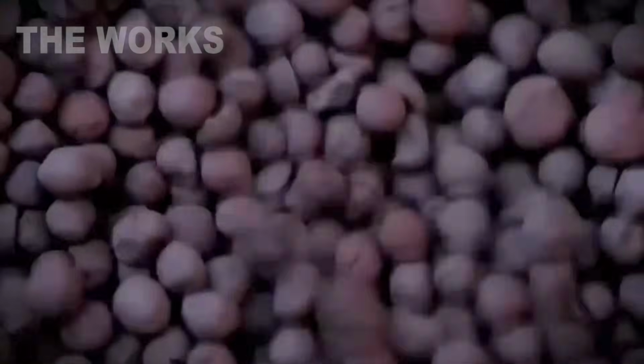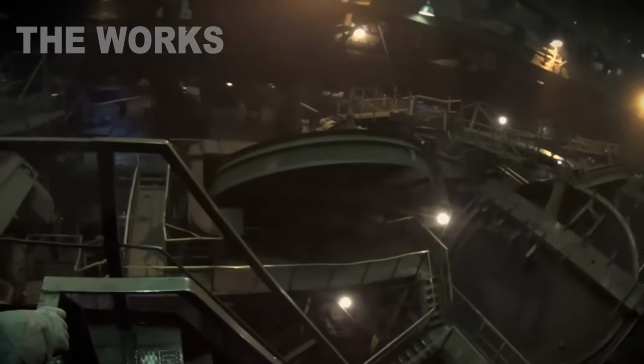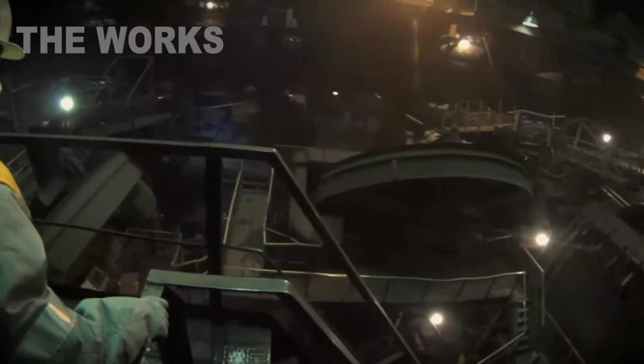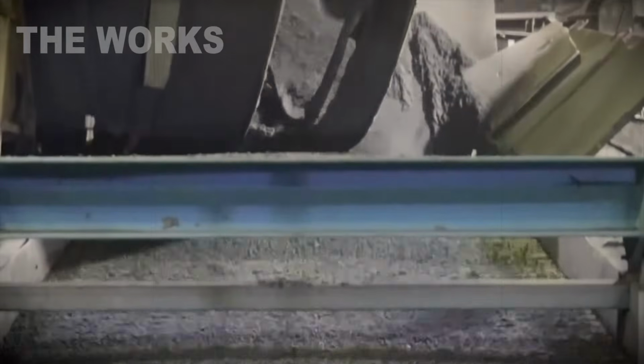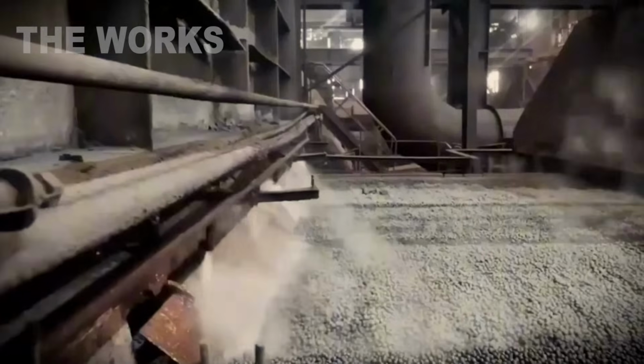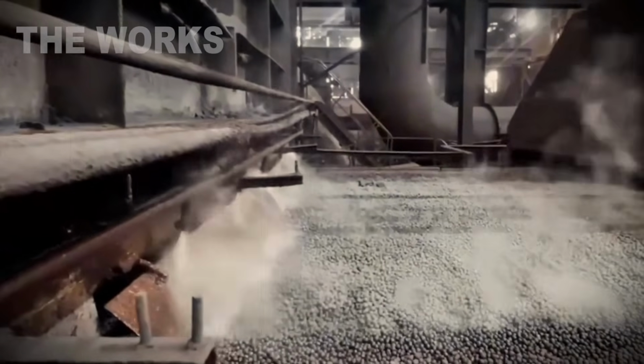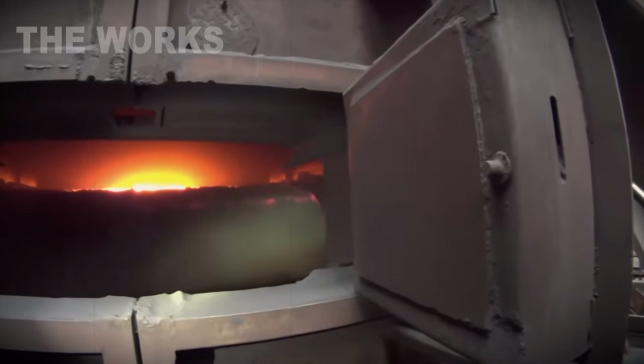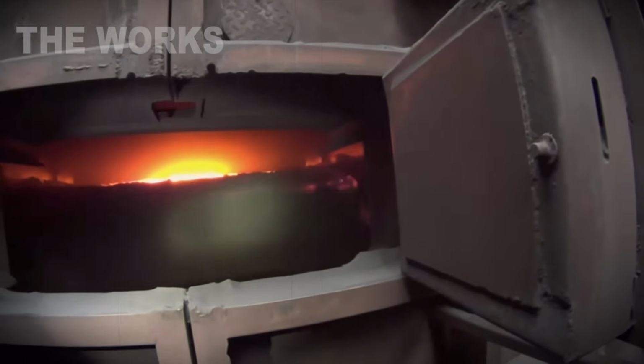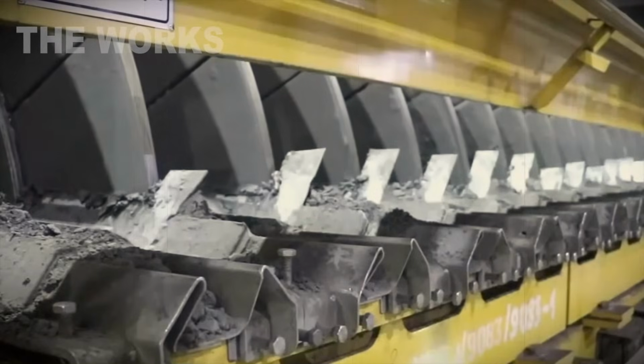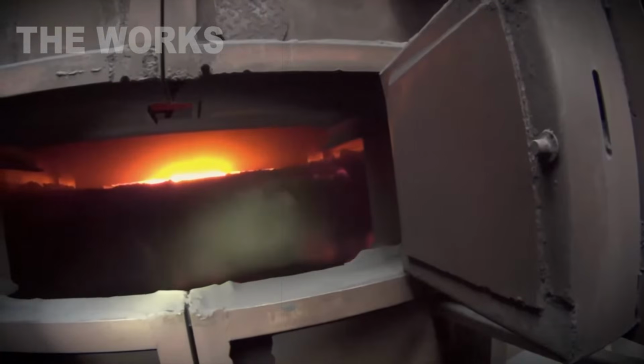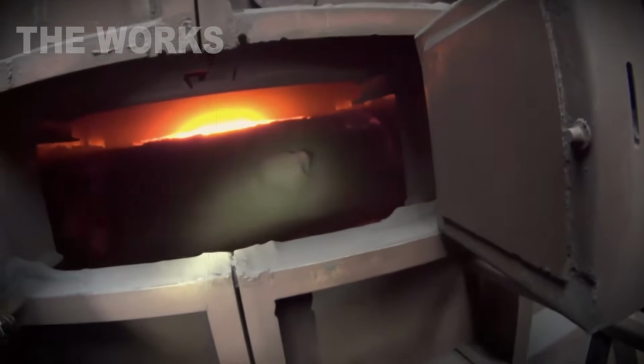The pellets roll off the edge onto a conveyor. Output? 300 tons an hour. 1 million pellets every hour. The pellets head to the kiln. Firing temperature, 2450 degrees Fahrenheit. 20 minutes in the heat. The pellets turn rock hard. Crushing strength, 3,500 psi. Now they're ready for the blast furnace.